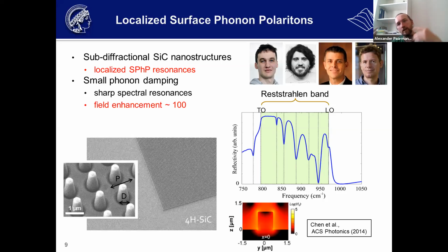where you see that in boron nitride, because of the hyperbolicity, the nature of the mode is significantly different. So we don't have these monopolar or dipolar modes, but you have these kind of standing waves of propagating bulk polaritons, and that's different from the fundamental physics, because these in silicon carbide arise from the surface polaritons, whereas boron nitride has these hyperbolic bulk-confined or volume-confined modes, and that's why the nature of the modes in nanostructures in boron nitride is also different.